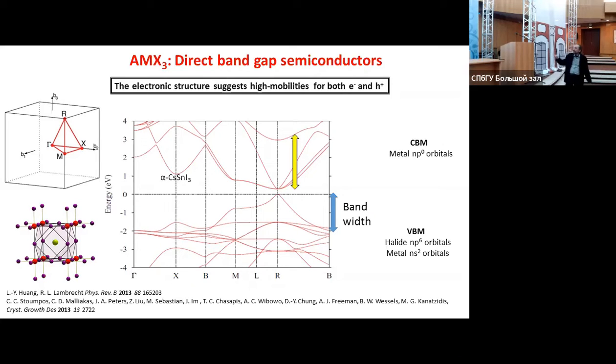And it's also important that, unlike most perovskites, this dispersion in the valence band is also huge. The reason we have a huge dispersion comes from the orbital origin of the valence band, which not only contains the halogen orbitals, but also the lone pair, the outer metal orbitals, which are responsible for this dispersion in this portion of the band structure.